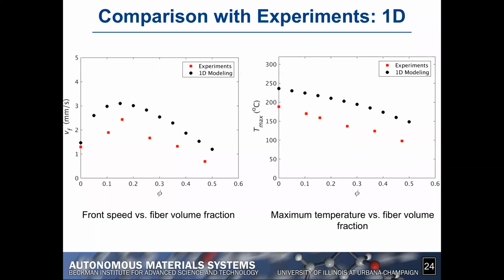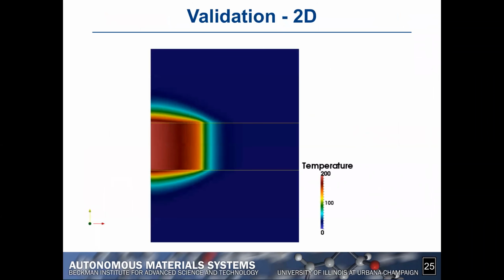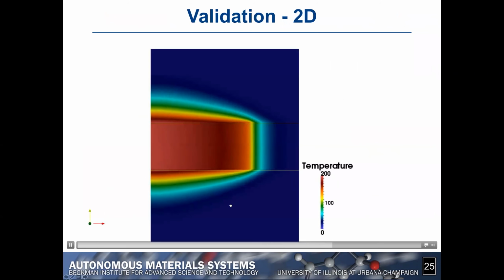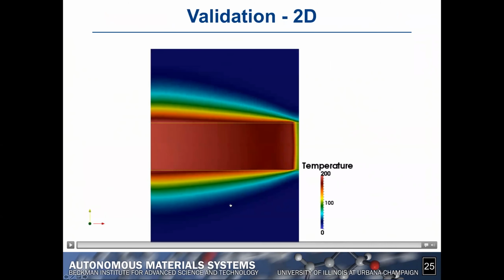The reason for this is that the 1D model is, by definition, adiabatic, meaning it ignores the amount of heat that is lost to the surroundings. And to capture this, we perform a series of two-dimensional simulations, which are shown right over here. On the top and the bottom, you have the support, which is a foam type of material that we use in the experiments. And in the middle, you have a layer of a composite system. We can see that as the front propagates through the composite, it actually loses some of the heat to the surroundings, as you would expect.